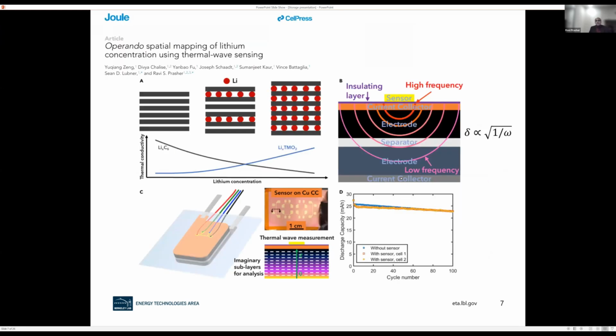So the question we started asking was, can we detect this concentration gradient operando? That means in an actual cell while the battery is working, right? It's very interesting. The thermal conductivity of these materials is a very strong function of the lithium concentration, okay? For example, in the typical lithium carbon electrode, which is the graphite used in lithium-ion batteries today, the thermal conductivity actually decreases as the lithium concentration increases for the graphite.